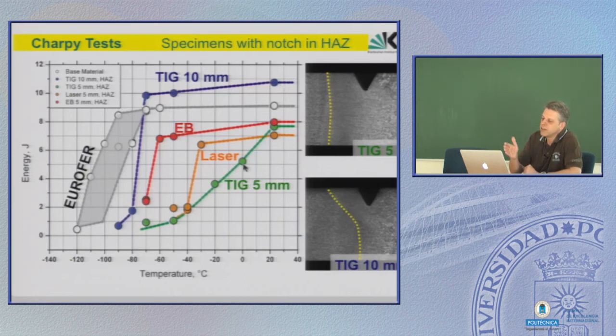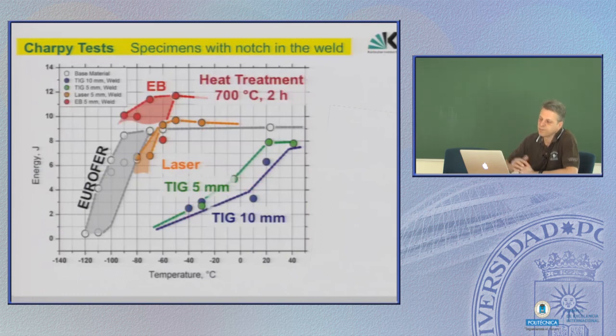But in general, you see, without any post-weld heat treatment, we have a severe degradation of material properties in terms of embrittlement. So these welds in Eurofer are in general brittle if you don't heat treat them. Then the same exercise again, but with a heat treatment. Here we started to examine if you could live with only one heat treatment as low as possible, keeping in mind the breeder unit specification.